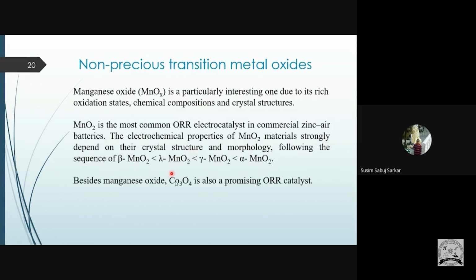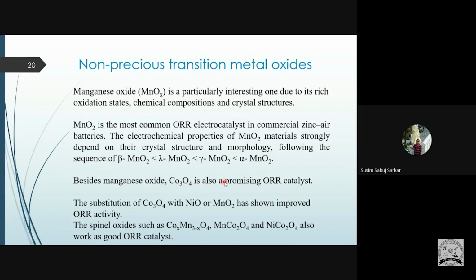Besides manganese dioxide, cobalt oxide also performs as an ORR catalyst. We can combine cobalt with MnO2 or NiO, and it has shown improved activity. The spinel oxide, what is called spinel, is actually a mixed metal oxide. Spinel oxides such as Co3O4, MnCo2O4, or NiCo2O4 are also very good catalysts. So these are non-precious transition metals.